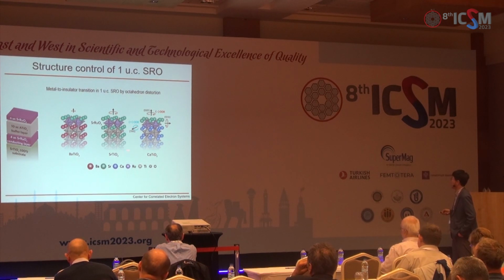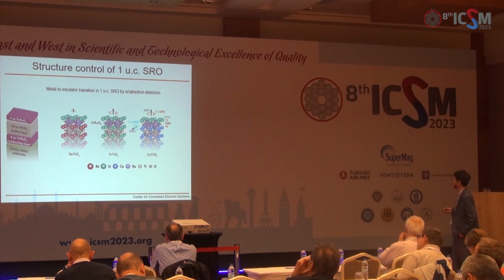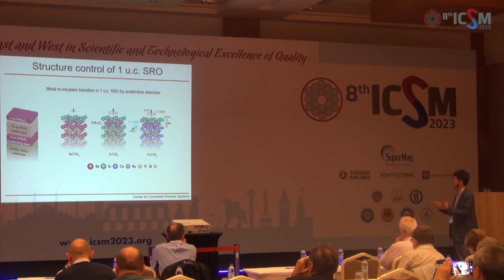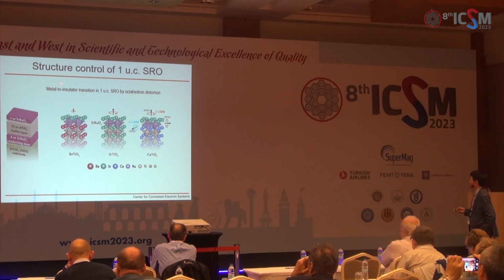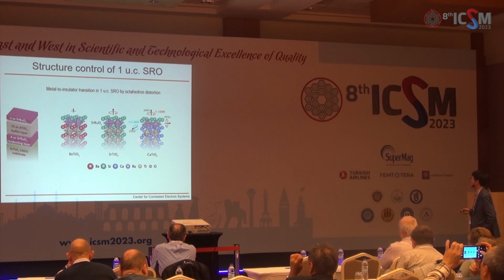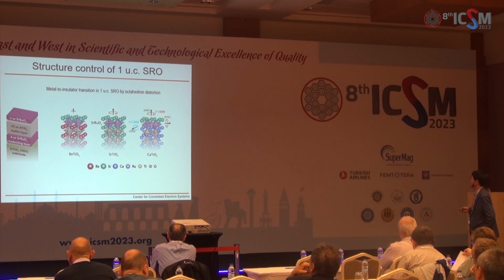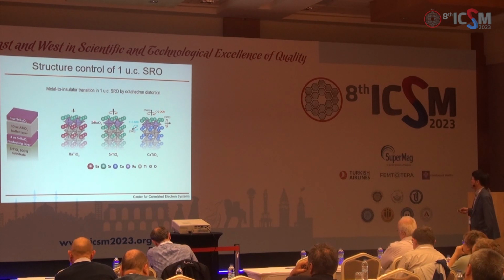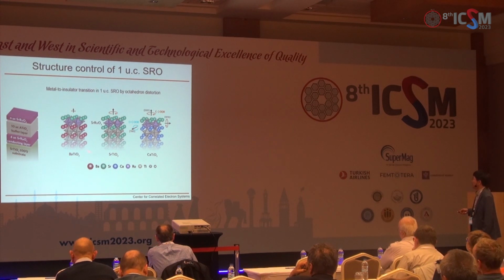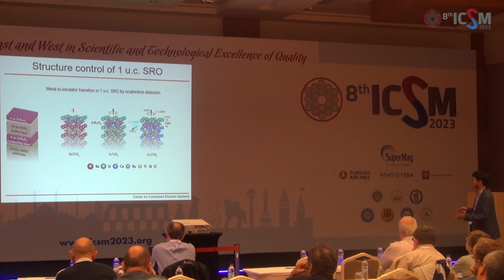For example, we can use calcium titanate, strontium titanate, barium titanate. This one has distortion. Meanwhile, even though this one doesn't have distortion, barium titanate has a slightly larger lattice constant, and that can provide tensile strain. So if we grow strontium ruthenate on top of these three substrates, this strontium ruthenate layer follows the distortion in calcium titanate. So this one has both rotation and tilting. Meanwhile, if you grow a single unit cell of strontium ruthenate on strontium titanate substrate, we only have rotation. And on barium titanate, this rotation is minimal, very small.